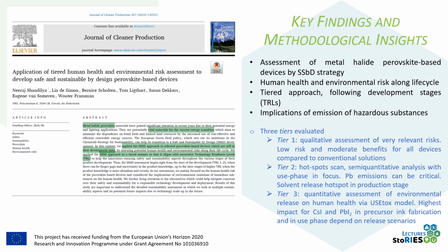What they found is that the highest impact is connected with the manufacturing, especially the precursor ink fabrication, for materials like some iodine, cesium and lead compounds. And regarding the impact over the use phase, this is highly dependent on the scenarios taken into consideration.